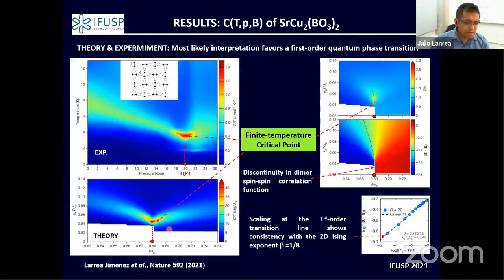And the theory also manages to reproduce the same type of quantum phase transition, given this sharp peak in the intensity of the heat capacity, at the ratio between these couplings in the dimer arrangement of 0.68.